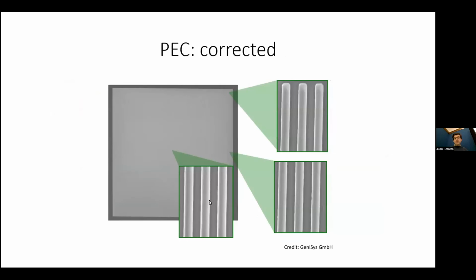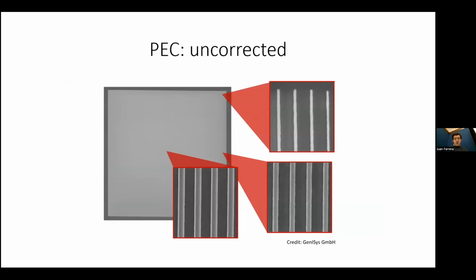And lastly, let me show you some patterns where you have a large grating that's been exposed without doing proximity effect correction. At the center, you can see that you have pretty good grating lines. At the edges, you can see that the lines are getting slightly thinner, but at the corner, they're really too thin. So the change in line width is pretty obvious.